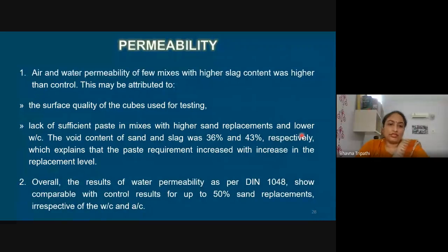So the machine which was used to evaluate the air and water permeability of the cover zone was the Autoclam, and it was highly dependent on the cover zone concrete only, which is limited to 25 to 50 mm. It was not testing the concrete core. That is why we have seen some deviation in results of the Autoclam permeability apparatus and the DIN apparatus.